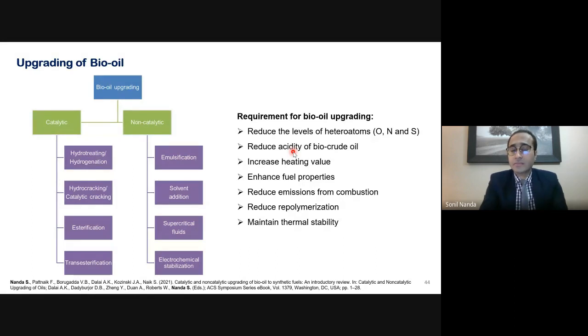It will also result in emission containing NOx as well as SOx. Therefore, it is very much essential to remove these heteroatoms. Now, the second requirement for bio oil upgrading is to reduce the acidity of the biocrude oil. Bio oil tends to be a little acidic because of the presence of acids and alcohols in the bio oil. And the acidity of the bio oil results in its instability and also its corrosiveness to the reactor itself.